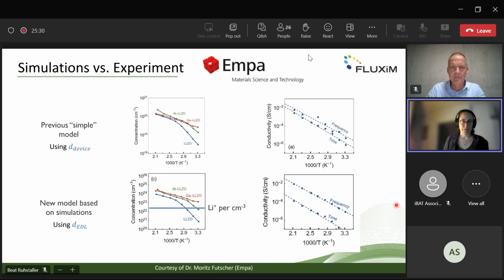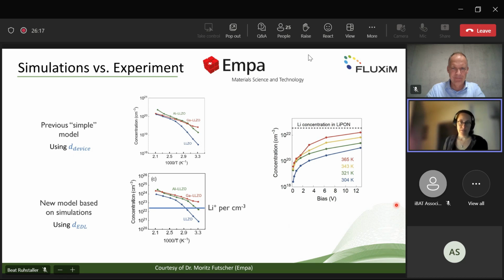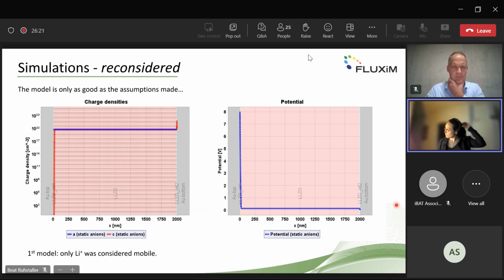And there was also another argument coming from the experimental point of view, namely when Moritz used this formula with the D device, with the thickness of the device, he got a very good agreement between the conductivity that he obtained from this transient current method compared to this frequency domain method, so the traditional electrical impedance data. And when he would use the new electric double layer thickness, he would get a discrepancy and also a huge concentration, which is even beyond the theoretical limit of lithium metal. So there was a clear argument why this cannot work. And also on the next slide, he even saw that this maximum really approaches also for other electrolytes the theoretical maximum.